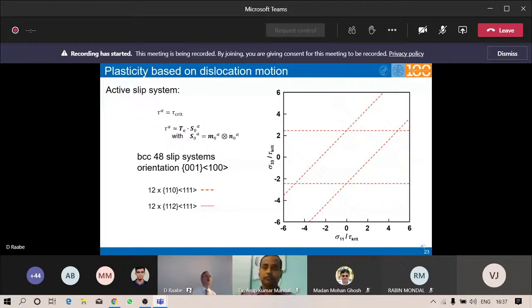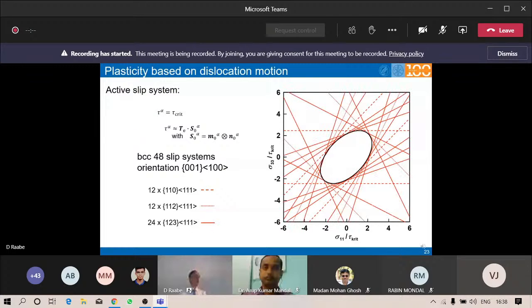When you add to this the {112}<111> systems, or even the {123}<111> systems, where <111> is of course the Burgers vector divided by 2, and the first indices are the glide planes, then you get a more complex shape of your local yield response. And again, all of these glide systems come of course with an individual strain hardening behavior that is described by these constitutive laws I described before.